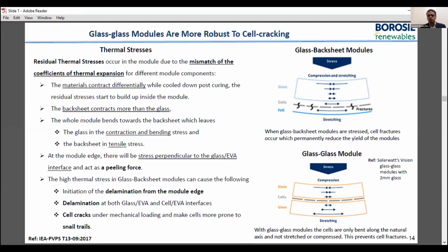So in this picture, you would see that since this backsheet contracts more than glass, the glass goes into contraction and bending stress, and the backsheet is in tensile stress. So these stresses are in totally opposite directions. Here the glass is in compression and stretching, whereas the backsheet is purely in tensile stress. So there are stresses that get developed.